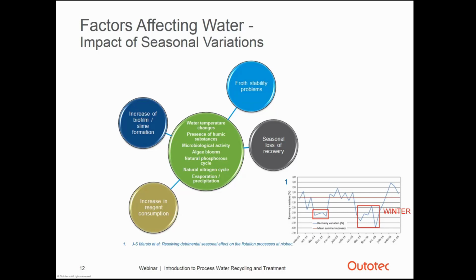accelerates microbiological activity. High microbiological activity can then be seen as algae blooming and slime formation, which can have a detrimental effect on flotation process. Temperature and pH variations in the water have impact on the evaporation occurrence, as well as on the precipitation and dissolution rates of different components. In lower temperature, the flotation froth can overstabilize, causing problems in flotation. You can see the graph on bottom of the slide where you can see there are some differences in recovery between summer and winter. The recovery is much lower compared to summer.